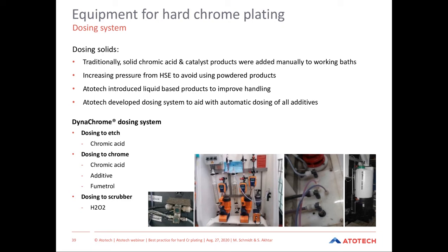Dosing is also very important. So with the new types of lines, the dosing system is getting more and more automatic. So manual additions of chromic acid and catalyst are not required. The dosing pumps are dosing the liquid chromic acid and the liquid additives inside the plating tanks, depending on ampere hours. So bath control is very, very stable.